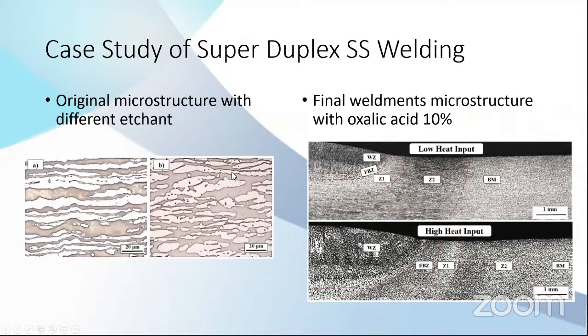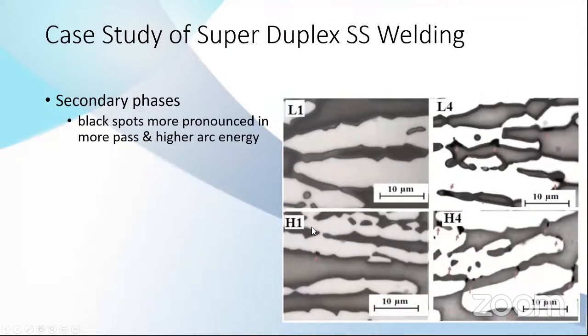If you see the microstructure, this is very balanced, very good. This is the original microstructure from the parent material. But when you see the weldment microstructure, for the low heat input and high heat input, you can see the effect. In the high heat input, you have a lot of secondary phase precipitation. Why? Later we can see it. So this is L, low heat input. 1 is 1 pass, 4 is 4 pass. You can see the effect of the heat input on microstructure.